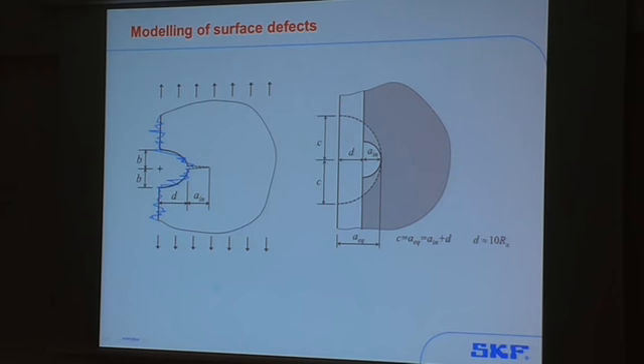Okay, now if we use that model to describe the rough surface and we also treat surface roughness as a kind of surface defect, then how do we model the defects? So we know that after machining, there are some micro grooves, but also some major grooves. So we model major grooves as a feature like a notch. And of course, for the material we can consider some very initial defects, which can be very small, in the micro size. If we make a cut of this plane, this shows how we model the defect. This is basically the depth of the groove, and then there are some initial defects that we can assume. Basically, this is the equivalent defect size that we take into account in the model for the solution.